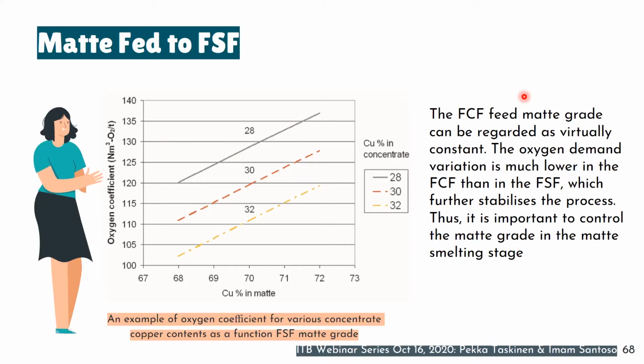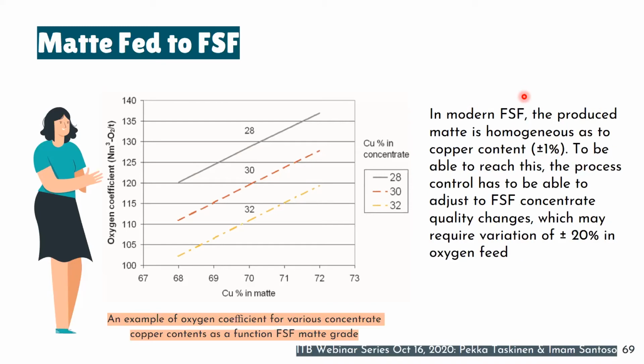And how to control the matte in the flash smelting furnace, maybe Pekka already mentioned, we can control it with the oxygen coefficient. In the flash smelting furnace, the variation of the oxygen coefficient can be 20% because the concentrate can vary a lot. It comes from different suppliers around the world. So the flash smelting furnace operation can accept that. The operation can vary around 20% in the oxygen coefficient, but it is different from the flash converting furnace, which needs very steady operations.